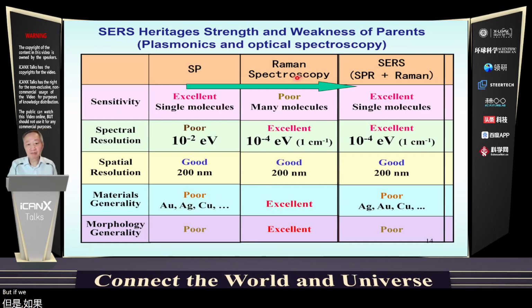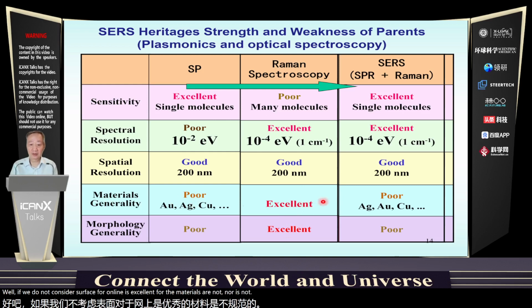But if we have this limitation, then SERS can get some strength from plasmonic and get some weakness from plasmonic. And the strength of Raman spectroscopy is its spectral resolution, or energy resolution, because we can have a very good spectral resolution as a fingerprint technique. So we can analyze many molecular systems. But the morphology generality for the Raman, well, if we do not consider surface Raman, it's excellent. For the material generality, of course, it's excellent.